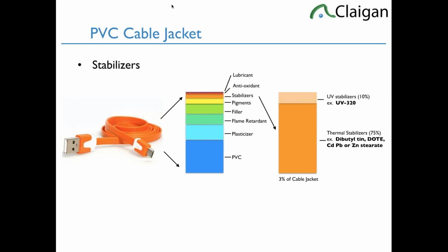But organotins are also a very common stabilizer and regulated either as REACH restrictions in consumer products or as SVHCs under REACH. But also a lot of PVCs have UV stabilizers. If the PVC is outdoor rated, it has to be outdoors, PVC absorbs UV light and then has trouble re-emitting it. And that can then degrade or create sun fade or sun degradation of the PVC. So outdoor rated plastics often have UV stabilizers like UV-320 or UV-328. The REACH SVHCs, the benzotriazoles. They're very common UV stabilizers. We don't see them that much.